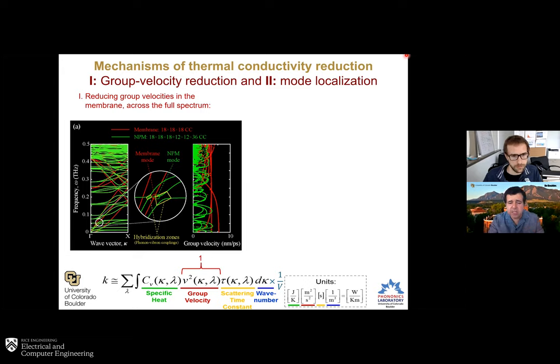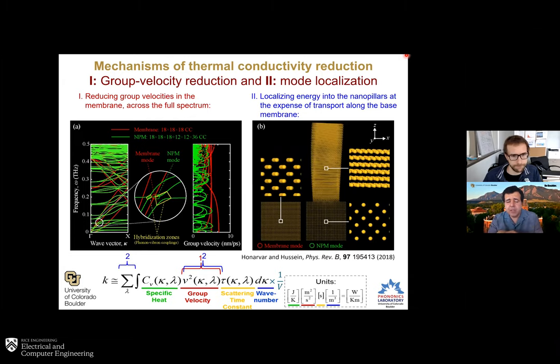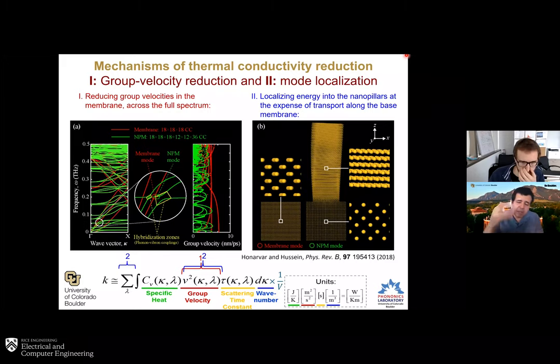That's one effect. The other effect is that we're adding these additional atoms, so we're adding to that summation on the left, right? But these atoms contribute modes that are flat, so they're effectively adding almost zero group velocity. And at the end, we're dividing by V. I should have mentioned this earlier, because thermal conductivity is an intrinsic property. So you get this localization effect where the energy gets localized in the modes, in the pillars, I'm sorry. And because of that, you get yet another mechanism that contributes to the thermal conductivity.